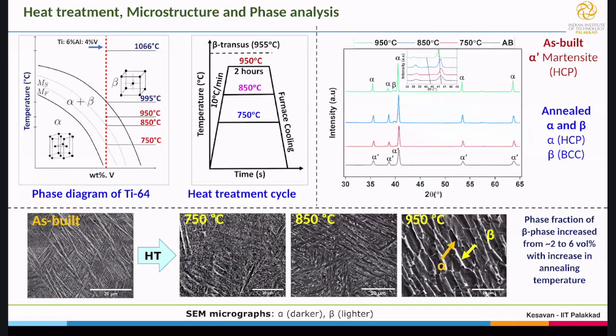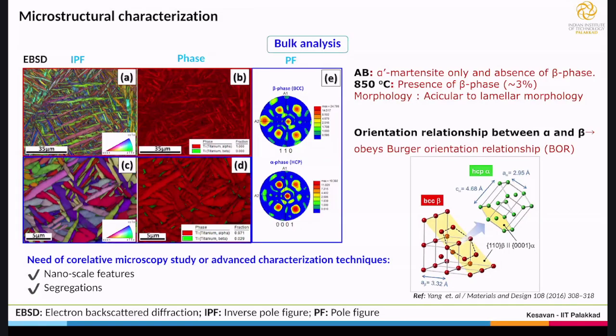Now we have also done EBSD. The structure you are seeing here is the EBSD structure of the as-built and heat treated samples. The as-built structure has lath martensite, and it is completely absent of beta phase. With the heat treated sample at 850 degrees Celsius, there is a beta phase, and you can see the phase fraction.